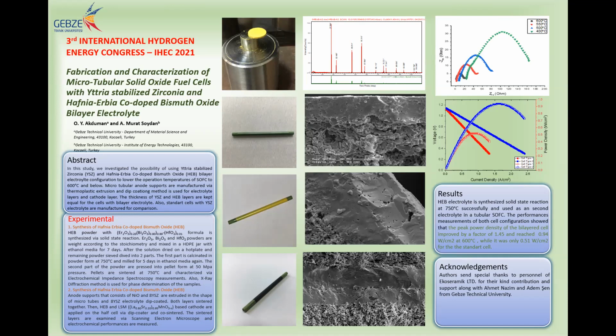So we analyzed the powders and the pellet form samples by XRD, X-ray diffraction method. And then it was successful. I'm not sure if you could see it from the diffraction data over there. And we continued to produce cells after we successfully synthesized the HEB powder.